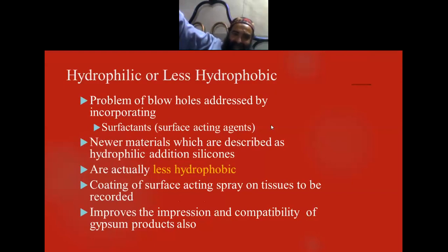But as the material has its own hydrophobic properties, actually these are less hydrophobic. So the surface acting agents, surfactants, should be coated through sprays on tissues that are going to be recorded. So this improves the impression and also the compatibility of gypsum products.